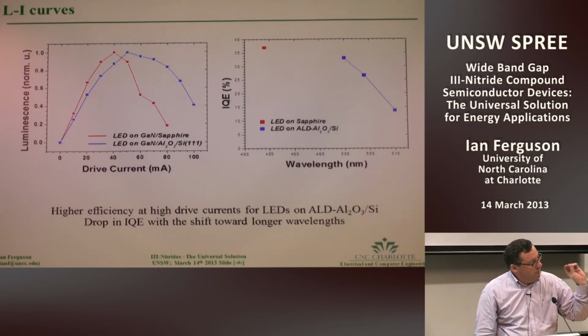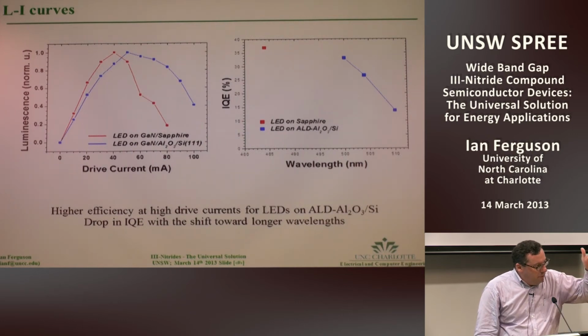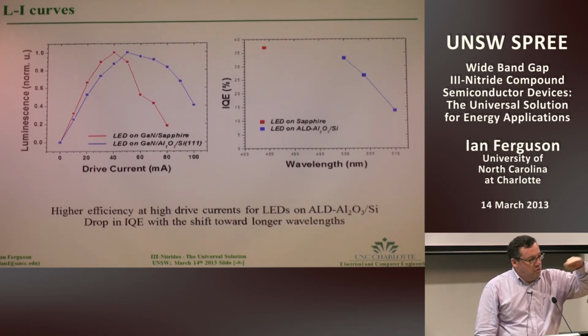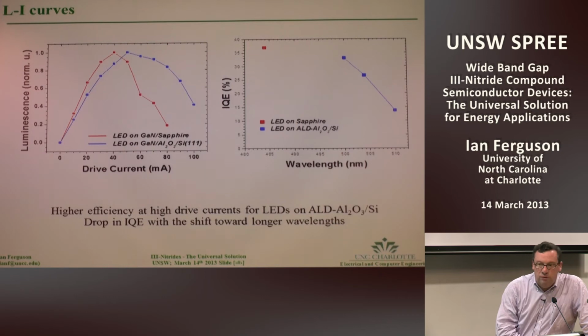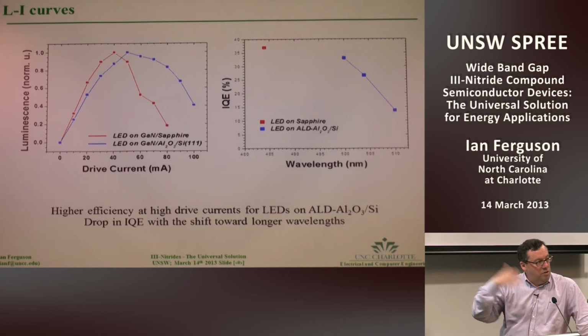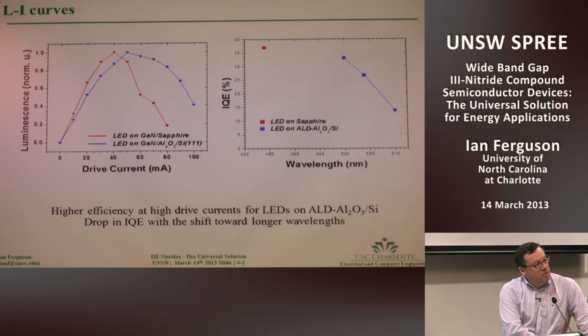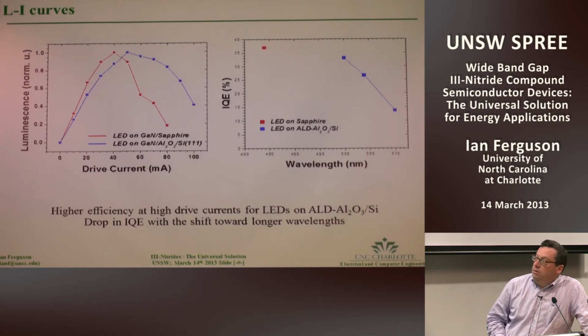Part of the reason the emission from these devices is strong is that when you grow the gallium indium nitride, it tends to cluster, the excitons localize, and they don't see the defects, and they kind of re-emit within these localized regions within the device. At some point, when you change the composition up or down, you start losing these compositional fluctuations within the material. These compositional fluctuations are somewhat of an issue when you come to solar cells. You need to get rid of them because your VOC collapses to the lowest value within the material. So when we started moving from LEDs into solar cells, the first thing we had to do was to learn how to grow the material uniformly at higher indium compositions, so we didn't see the VOC collapse on the devices.